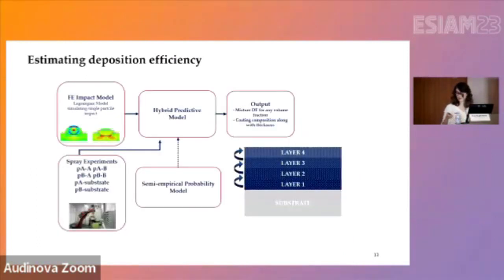We have developed a hybrid experimental, numerical, and probabilistic method in order to be able to estimate the deposition efficiency and the chemical composition of the deposit when we are mixing different powders. So starting from a single particle impact in order to obtain the flattening ratio and the area that would be covered by a single particle, performing a series of experimental tests to find the probability of adhesion of each particle to the same material or to the other material or to the substrate, so the mutual interaction.